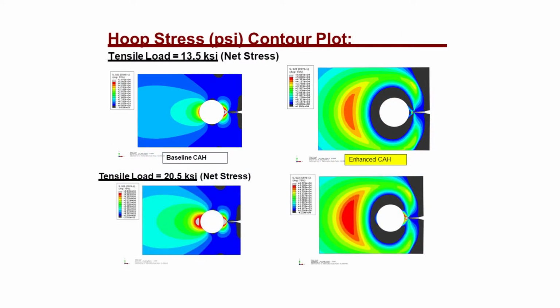Now if we put those coupons under load, you'll see that the hole that is not treated is just a hole with nothing in it. You've got the tensile forces all around the hole itself, and so that's what's going to be acting on that crack, right? Those tensile forces are right there. But with the treated hole, with the crack arrest and the bushing, the tensile forces, again, are pushed way out, so that we have the 13.5 KSI here, 20.5 KSI there. So the FEA supported our assumption of what was going to happen.